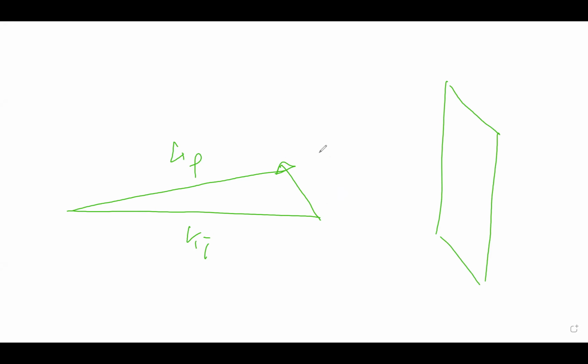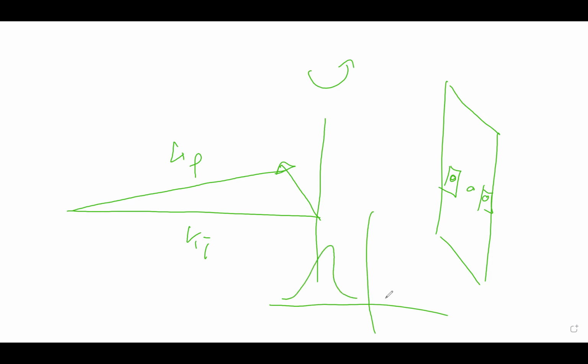And then we do a rocking scan. So we have the sample. We rotate here, and then we have a Bragg spot here, and we look at that one, and then this one. And then what you'll get is the rocking curve, which looks like this. And then you extract this length by fitting your rocking scan. And if you look in Q space, this is essentially the scan we're doing.